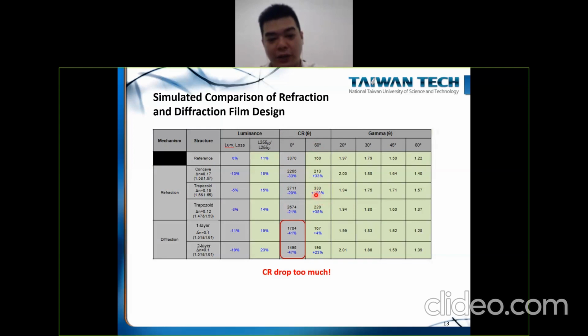Based on these design targets or conditions, we can try to compare diffusion films with different structures. You can see that by comparing the refraction structure with the diffraction structure, the sacrifice in the normal direction is less for the refraction structure. So this one is more ideal for designing the diffusing films for the VA display based on our requirement. For the diffraction, because there's no selective light diffusion, the contrast ratio drops too much in the normal direction. And in the large angle direction, the contrast ratio enhancement is not as good as the refraction film.